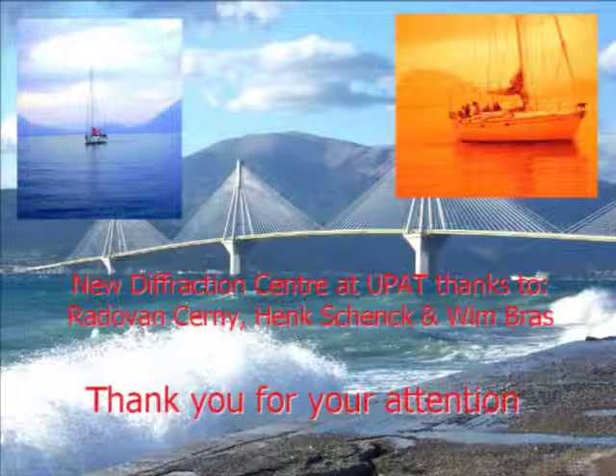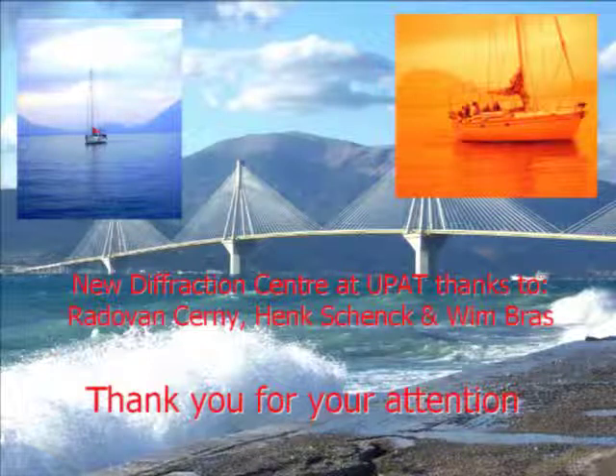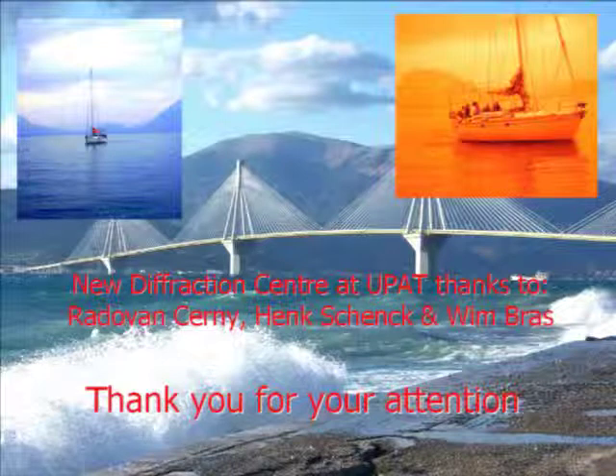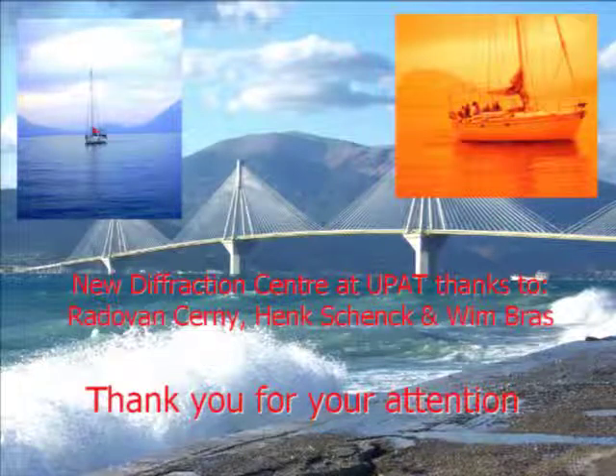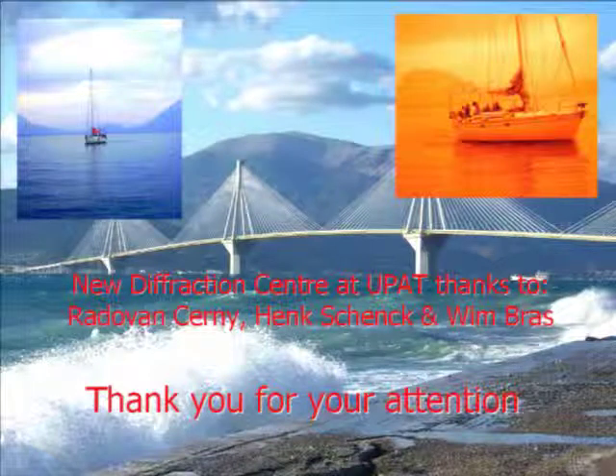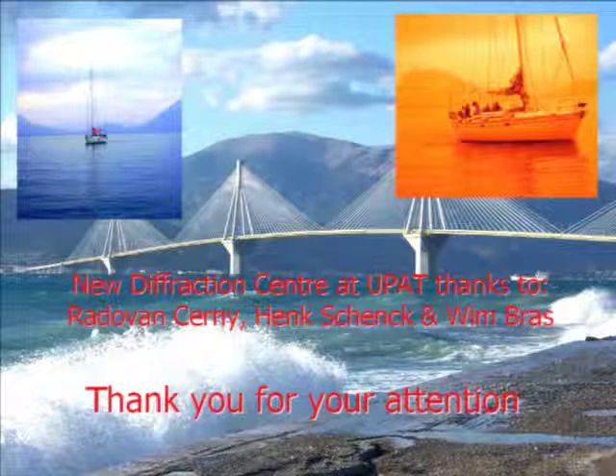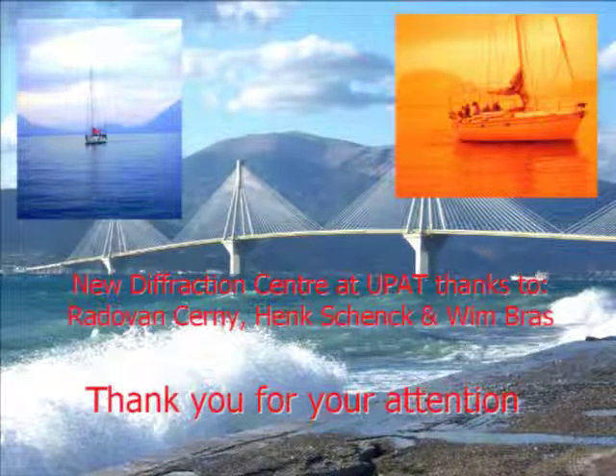We work at soft energies on ID31 just to improve the peak shapes and to spread out the patterns. Of course, the samples suffer more from radiation damage at soft energies, but we get better, more spread out patterns. It's only John at ID11 who has the flexibility to move away the detector. That's how he can work at hard energies. But at ID31, it was not possible.